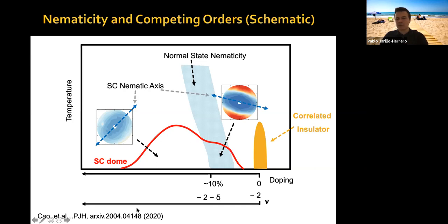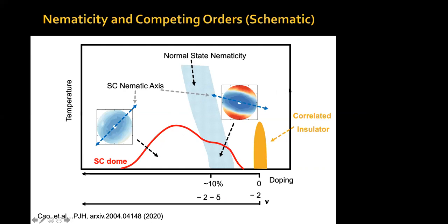You have the continuous evolution of how the angle is varying for every doping and at different temperatures in this paper, okay? Between the average angle here and the average angle here, this seems to be about 60 degrees. Again, there's a range, the angle between here and here varies between 60 and 90 degrees, okay? So it's a strong variation of the angle, and it's mostly rapidly varying there, okay? So it's hard to say that it's fixed to some external strain or...